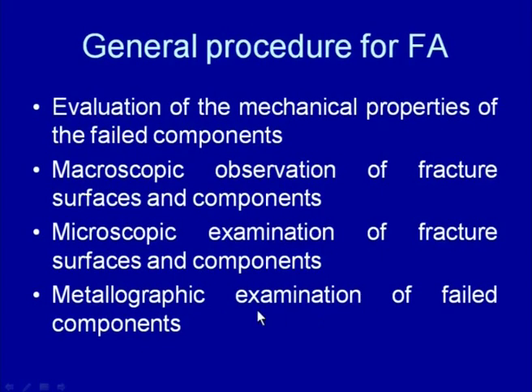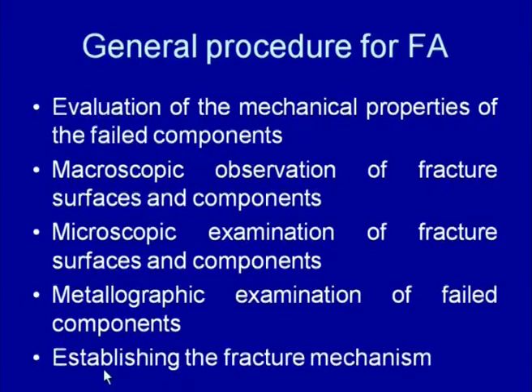Further, image analysis of the metallographic microstructure can give us information about whether grain coarsening has taken place during the exposure, or the kind of microstructural features which are present in the component. Then establishing the fracture mechanism: if the defect was already there in the component, then in light of the service load conditions, whether it should fail with the presence of those discontinuities or not.